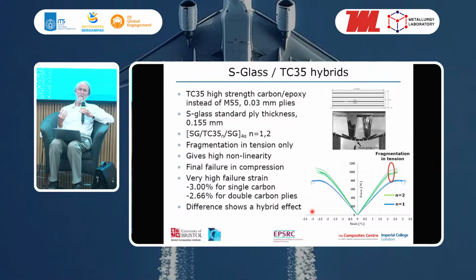A hybrid effect is a term where we see one material goes to a higher stress or strain when hybridized with another material than it does on its own. And in this case here, it's because the failure is controlled by instability, and when we have less carbon or more glass, then we have more support to those carbon fibers against an instability failure. So we see a change in the failure strain as we change the ratio of carbon to glass. So this is because the compressive failure is not a strength-dominated failure. We're not reaching a critical failure stress. What we're doing is we're reaching an instability, and instability is really a structural phenomenon, and it depends on the boundary conditions, on the support available to the different materials.